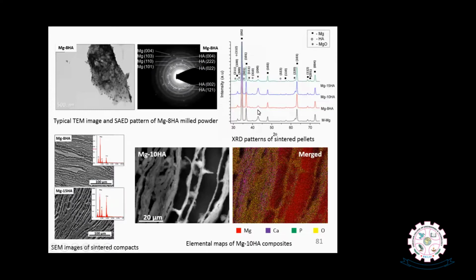And after sintering, we clearly noticed the retention of hydroxyapatite, the stability of the hydroxyapatite phase as it is in the sintered composites. And then we observed the formation of a lamellar structure, microlamellar structured composites, because the ball milling deformed the magnesium particles into thin flakes. The thin flakes were then sintered, and the sintered structure shows a lamellar microstructure here. One typical elemental mapping also confirms the presence of calcium and phosphorus in these composites.